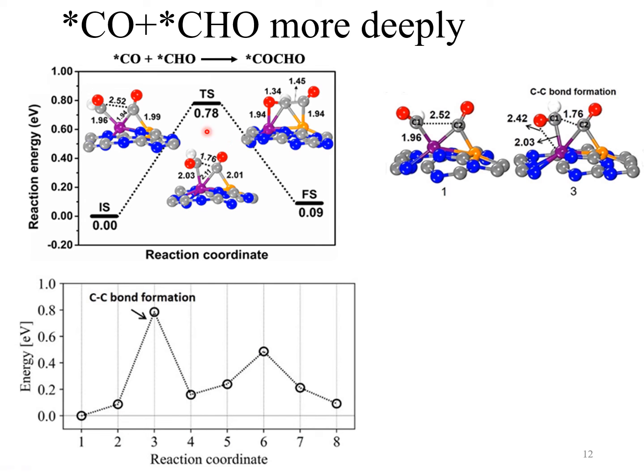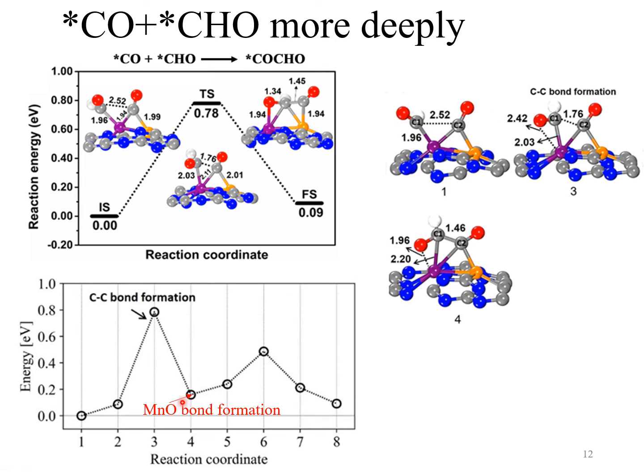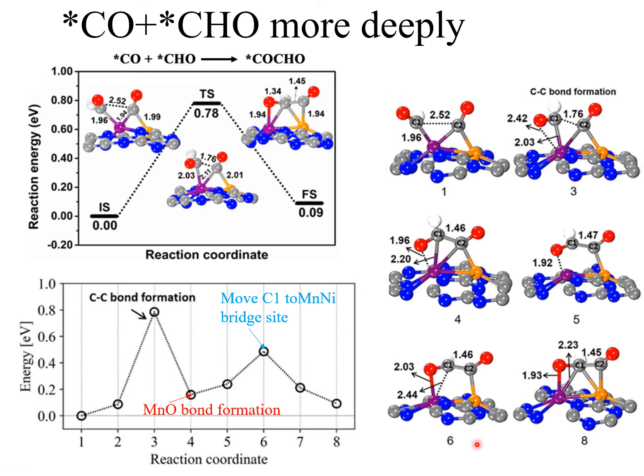We are looking at this reaction more deeply. Here is the initial state, transition state, and the final state. Here I'm presenting a more detailed view of the reaction process. We can see this high barrier of about 0.8 eV is 3, the CC bond formation process. And then at 4, we will have a manganese oxygen binding. And then at 5 and 6, we see that the C1 carbon moves into this bridge site, making a very stable reaction product.